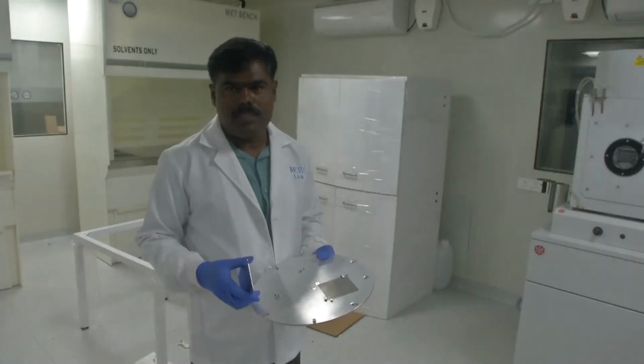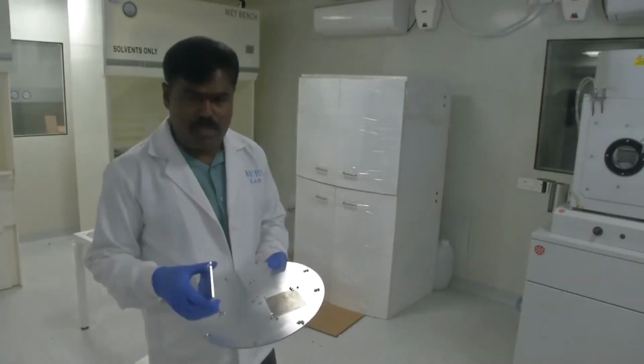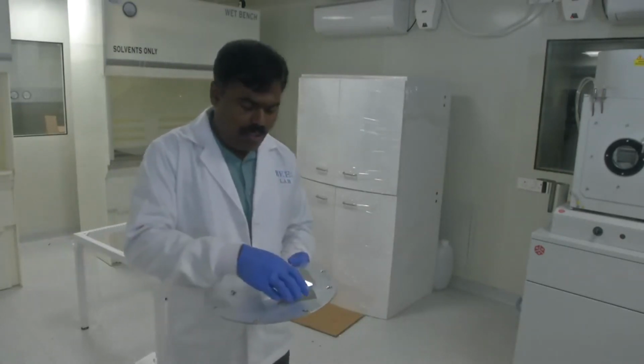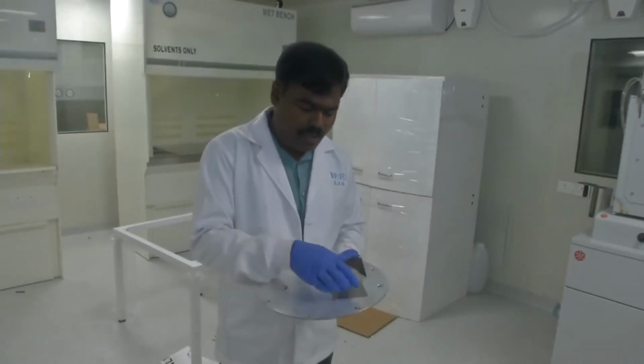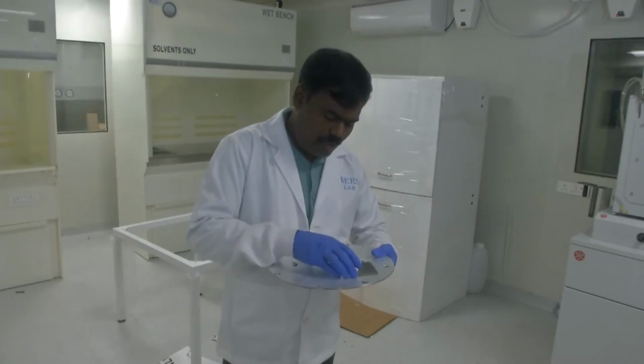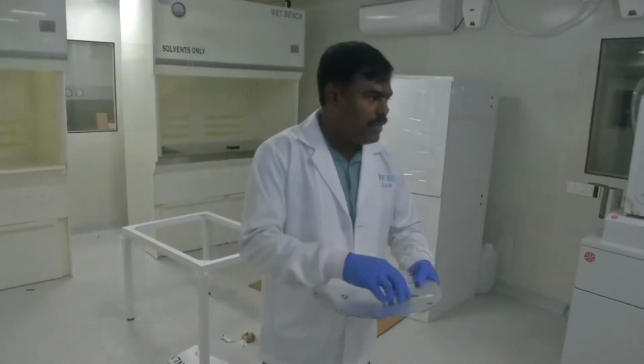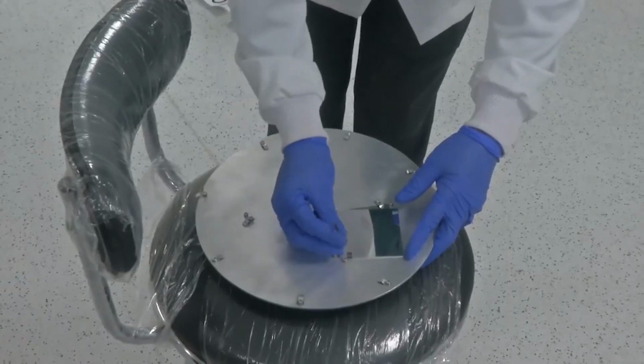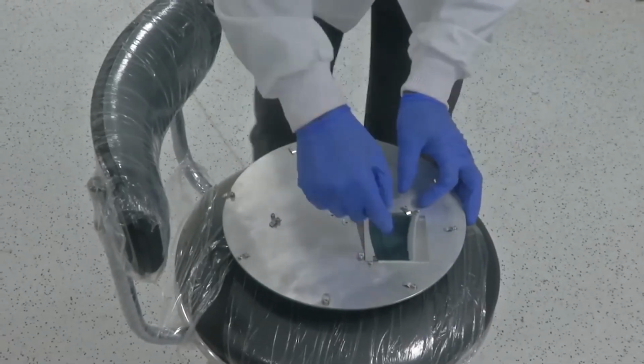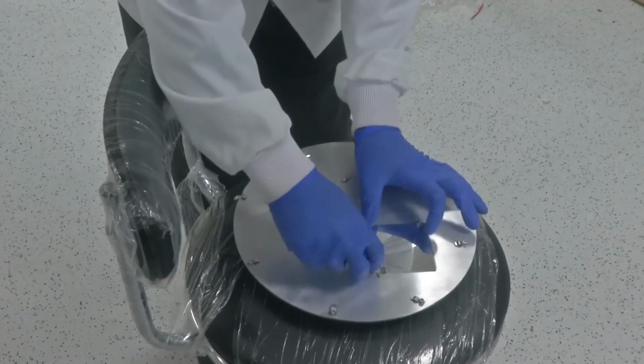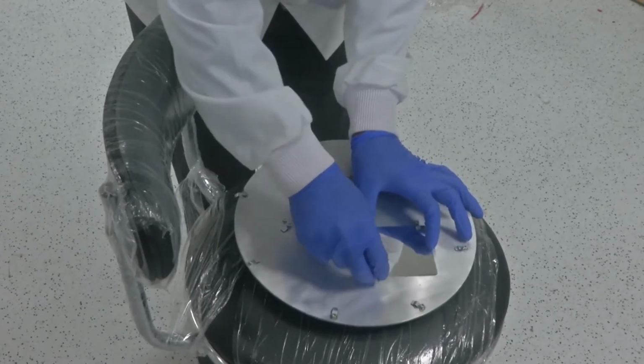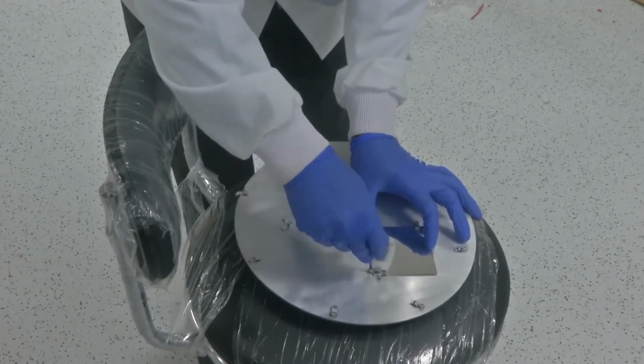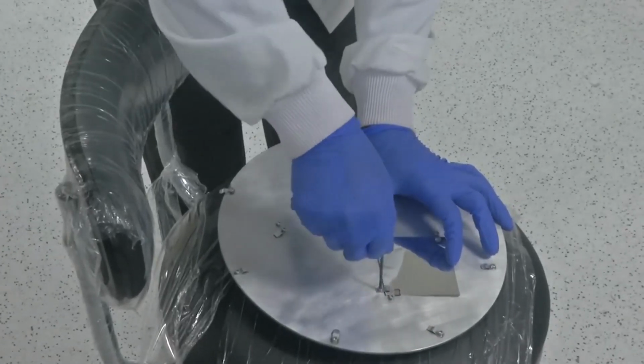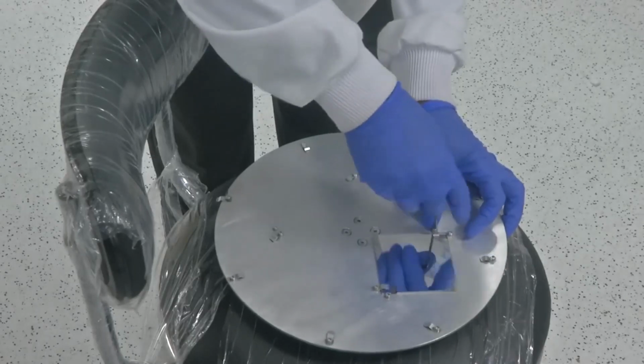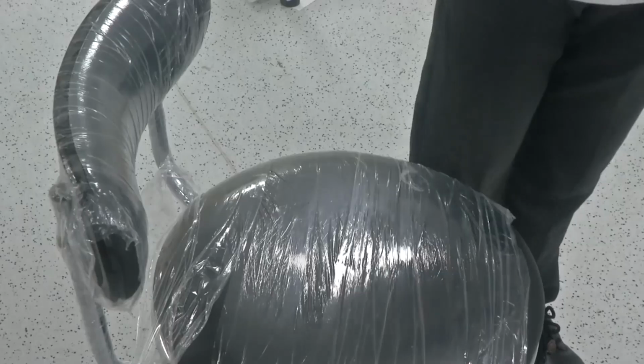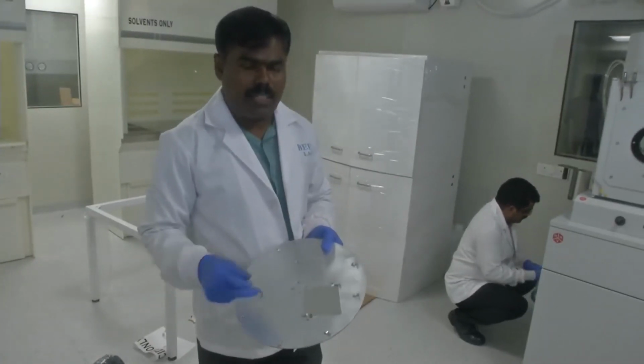Now I am going to load the samples. Take a clean glass, 1 inch, 2 inch or 4 inch, whatever you need. Place the glass here. Don't remove the clamp, just open it slightly. Then tighten the screws using Allen keys. Now your substrate is fixed on the substrate holder.